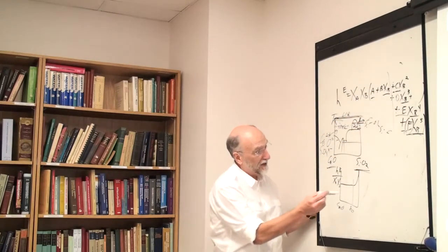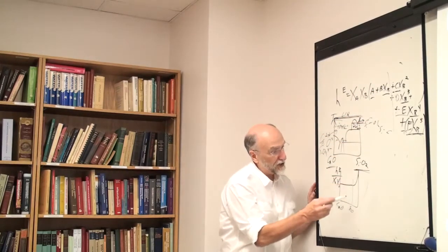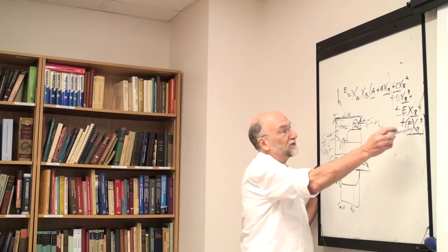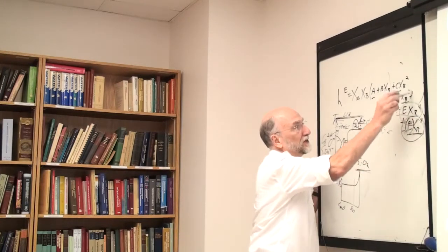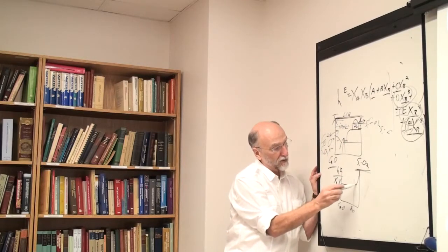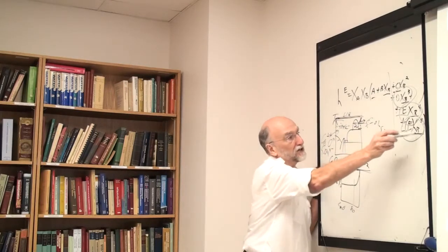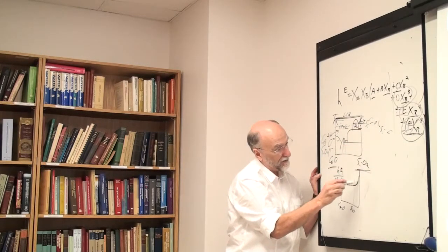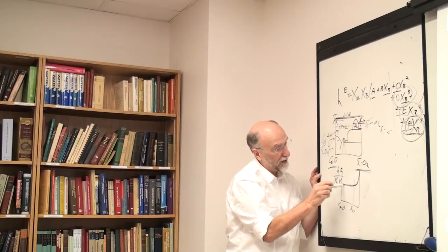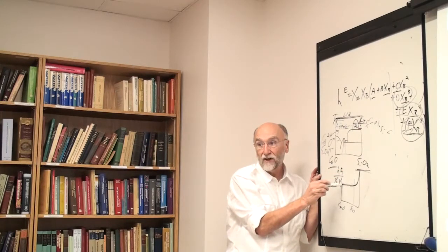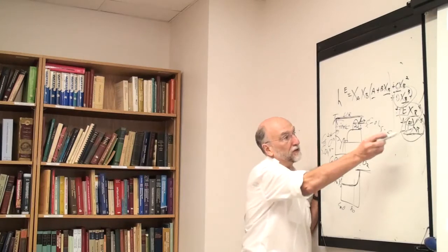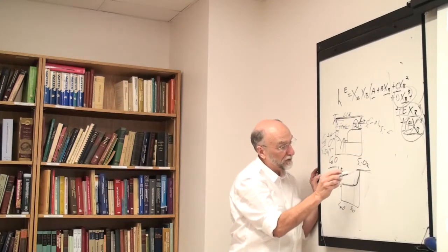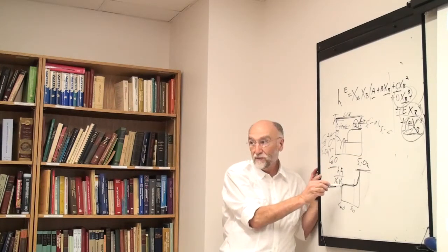The reason being that if you use the Redlich-Kister terms, well, as I said here, in these terms, the big terms really have only an effect over here. So now you can add not two big terms here. They will have the effect you want over here, and they won't change this very much at all. And that's what you want. You don't want the terms that you're adding to try to fit this region to start to mess up the very simple linear relationship over on that side.